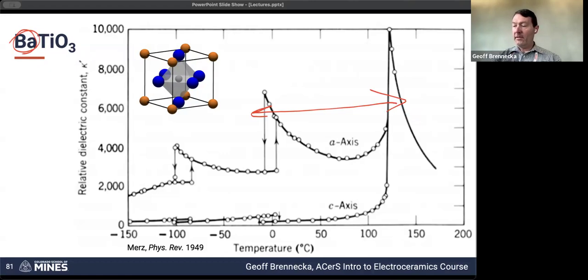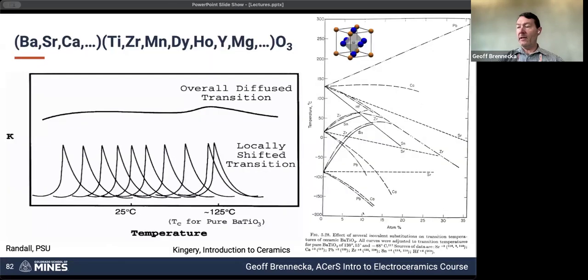So what we end up doing is doping barium titanate with a gazillion different things, about a third of the periodic table, so that we end up with this chemical soup, so that we've highly optimized exactly what the intentionally heterogeneous sample does, so that different regions are going through these phase transitions at different times to end up smearing out that phase transition series. And so these are largely to shift the temperatures at which each one of those transitions is happening. Zirconium in particular pinches the phase transitions together.